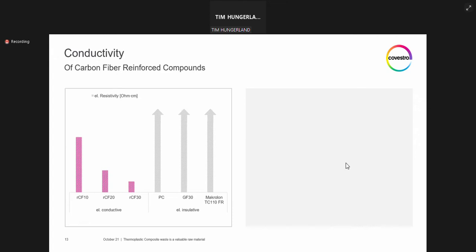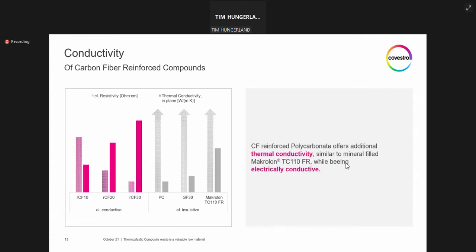Shown on the left side of the graph, with increasing amount of carbon fiber, the electrical resistivity drops, which means the conductivity goes up. Compared to that, the insulative materials on the right side have a higher resistivity and therefore no electrical conductivity. Another benefit that comes along with carbon fiber reinforced plastics is the ability to dissipate heat and therefore act as a sort of heat sink. This thermal conductivity comes in handy as well when you need to reduce the surrounding part temperature, for example, in electronic devices. As you can see in the graph, the thermal conductivity goes up with increasing carbon fiber content as well. The combination of electrical and thermal conductivity makes this product class a useful addition to, for example, our thermally conductive but electrically insulated polycarbonates, such as Macrolon TC110FR, as shown on the right side.